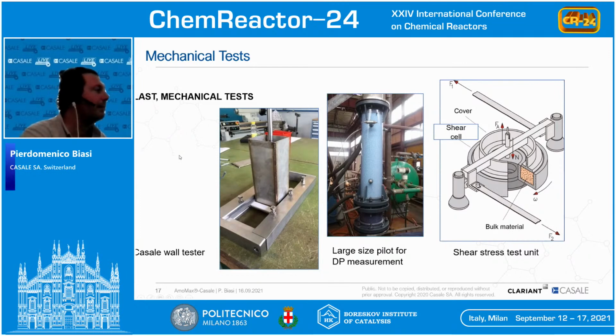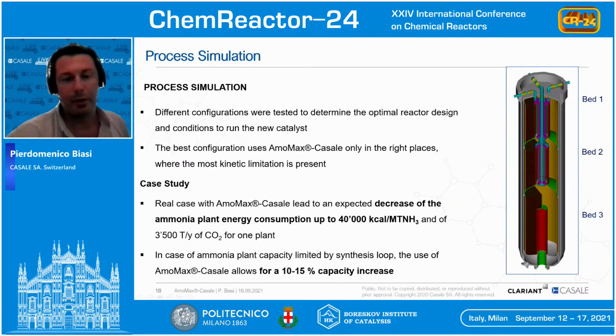So given the positive results, we passed to the process simulations that were done in our process department. We determined the optimal reactor design and the conditions to run the new catalyst. And we saw that the best configuration was to use the AmoMax in the right places, and also where there are some kinetic limitations. What is important is that we then optimized the reactor to make this new catalyst profitable.